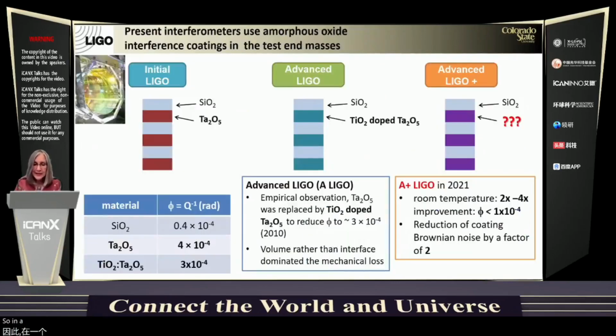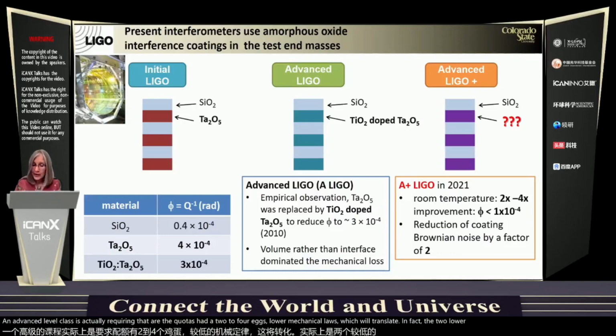In the present interferometers, called advanced LIGO, the interference coatings consist of a stack of silicon dioxide and titanium-doped tantalum pentoxide. In this pair, it is the high index layer that has the highest mechanical loss. Silica has about a factor of 10 lower mechanical loss. So all of the efforts have been devoted to understanding the origin of mechanical loss and reducing it. There is a roadmap for the development of coatings for next generation gravitational wave detectors. Advanced LIGO Plus requires that the coatings have 2 to 4x lower mechanical loss, which will translate into a factor of 2 lower thermal or Brownian noise.